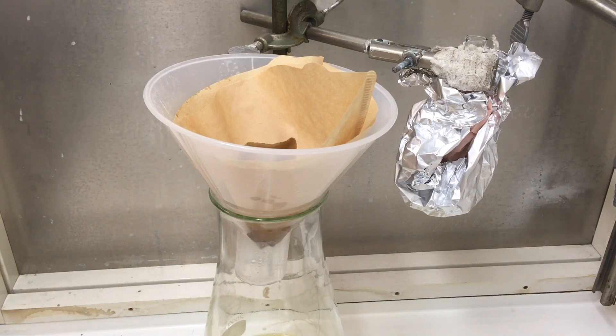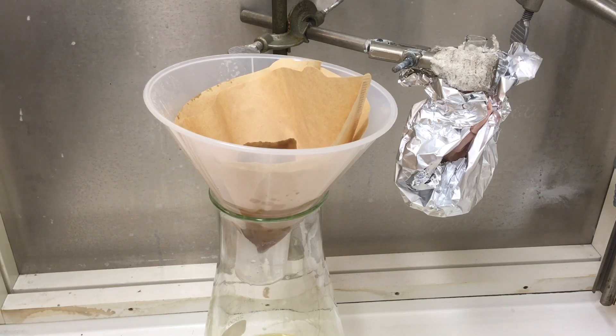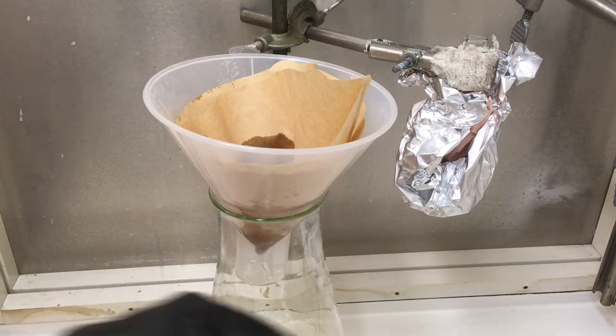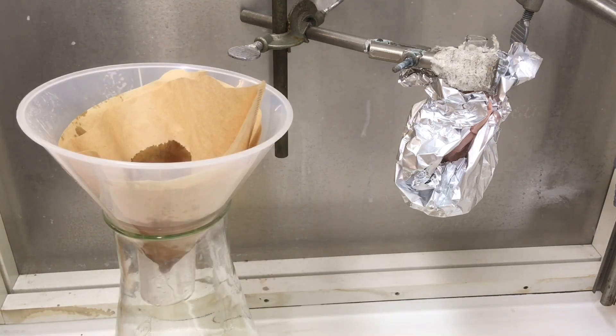You can take your solution now and start pouring it in. If the solution is too hot, then you will break the filter paper immediately, so you have to be a little bit careful in the beginning when you do this. Some of this froth that you see on the top of the surface from your Mr. Muscle sodium hydroxide can actually be removed by skimming it off, and then you get less of a problem when you filter it. Now I will just dilute the one and a half liters I get here five times, so I get approximately 20% solution of sodium hydroxide.